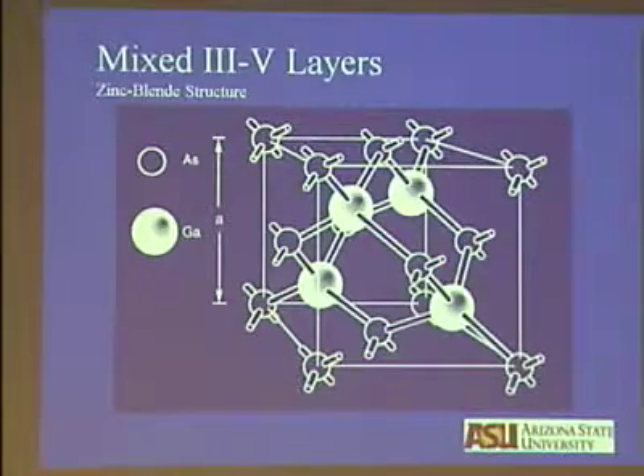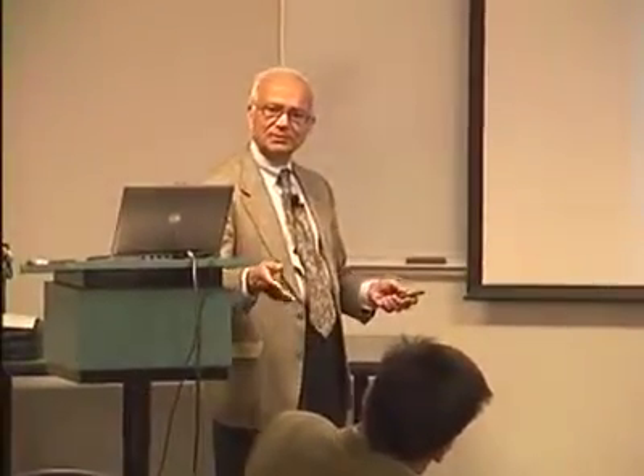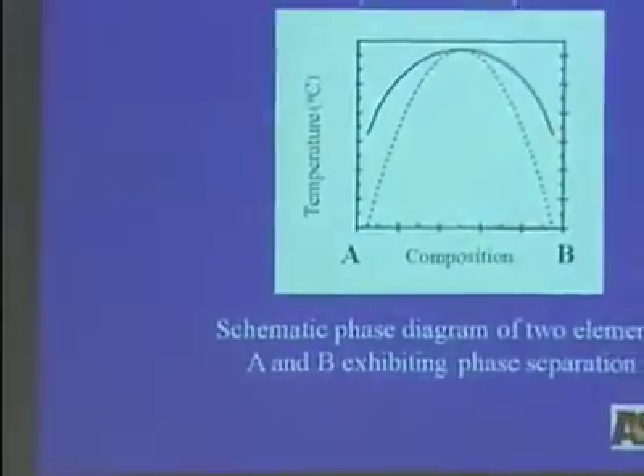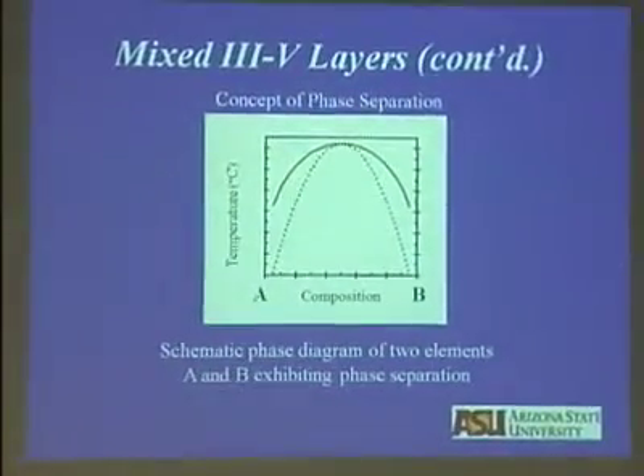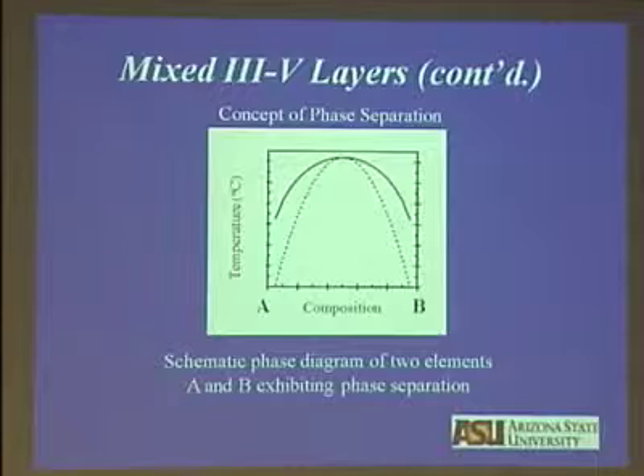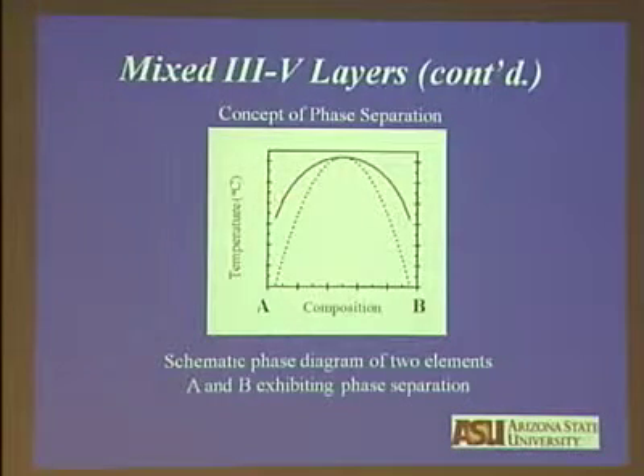Self-assembly to the metallurgists has been known forever. You take aluminum copper, you form copper-rich precipitates in aluminum alloys. And what has happened is it has been fashioned into science by the word self-assemble. And we material scientists have known self-assembly for a long time. Now, just to give you the background, what is phase separation? Phase separation is, you have a solid solution, and that composition free energy diagram has inflection points, and you cool that material. It doesn't get to these end members, but the solution decomposes into A-rich and B-rich regions. That's what we refer to as phase separation in material science.